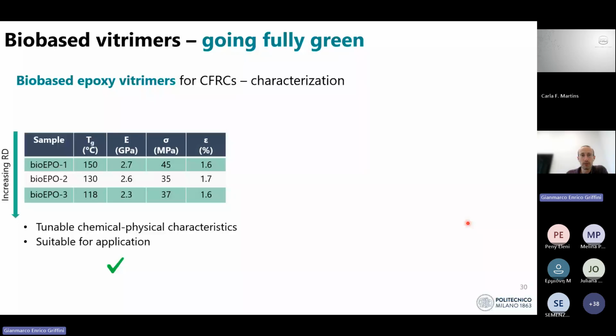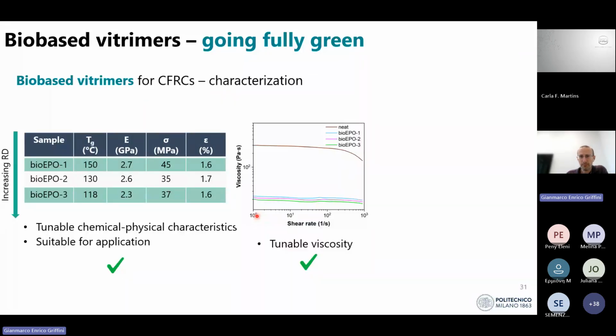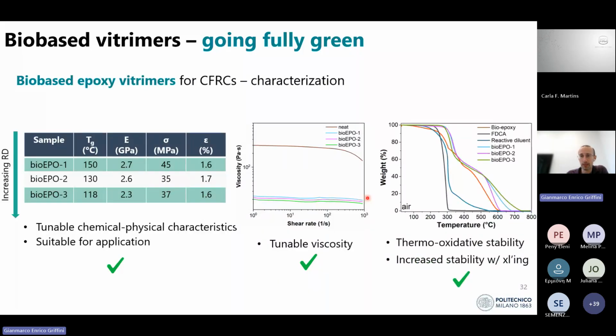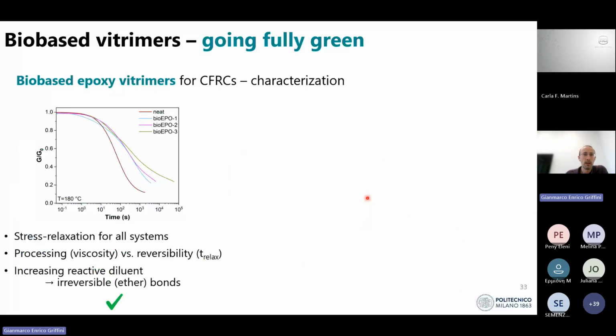We included a catalytic system to, again, promote transesterification reactions, which were then evaluated on the cross-linked material. So the material, again, could achieve glass transition temperatures and mechanical properties which are aligned with typical epoxy-based systems for reinforced composites. By modulating the amount of reactive diluent, we could obtain a significant reduction of the viscosity compared with the previous system, which is also good for processability in fiber-reinforced composites. And also, all the materials exhibited very good thermo-oxidative stability, which was found to increase by increasing the cross-linking network. Stress relaxation was found for all systems.